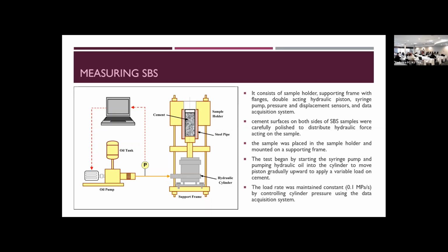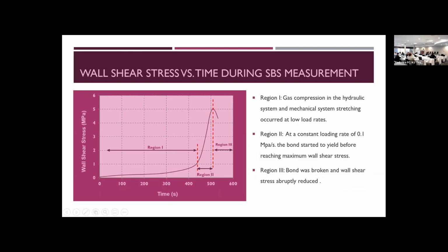By increasing the axial force, or the push-out force, with a very controlled speed, we've been able to record the data. As you can see here, the data for this test was recorded up to a maximum value, and then whenever the sample was failing in terms of bonding strength, we stopped the test. That's why, as you remember in my previous paper, we continued this debonding until the entire cement sample was pushed completely out of the steel, just to learn a little bit more from the experiment.